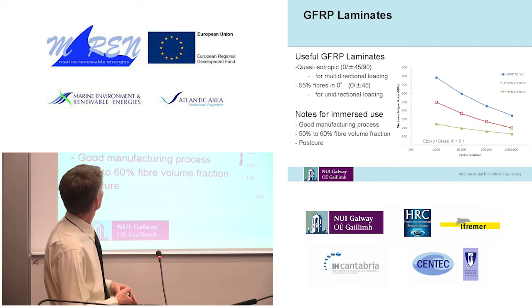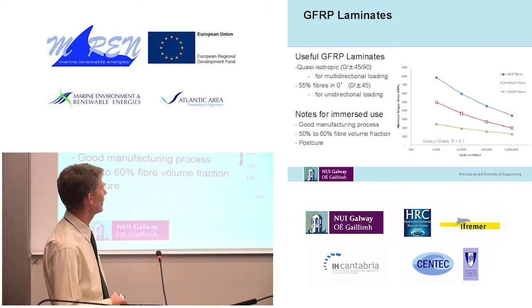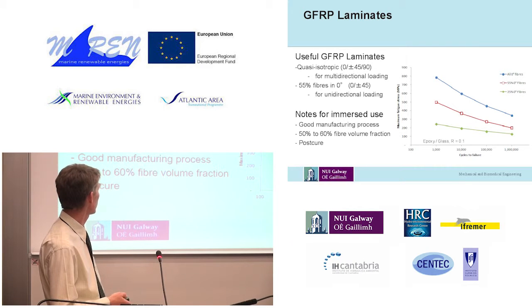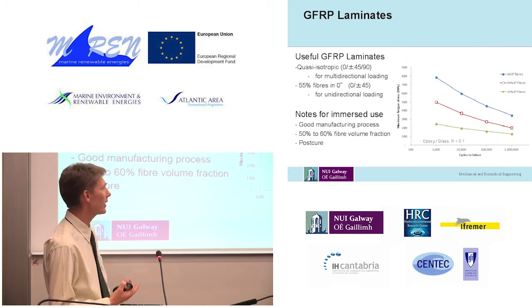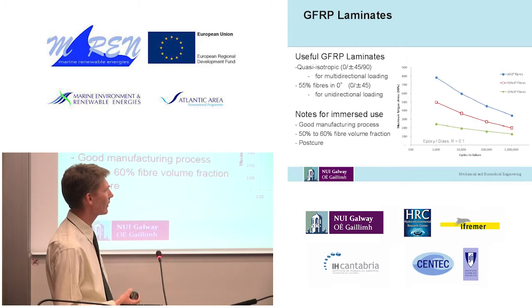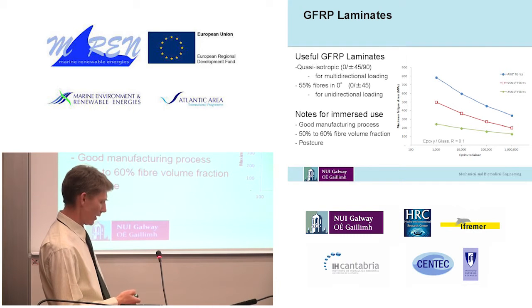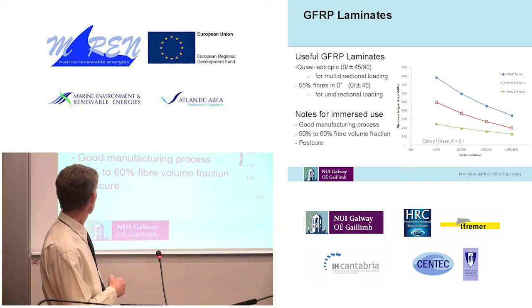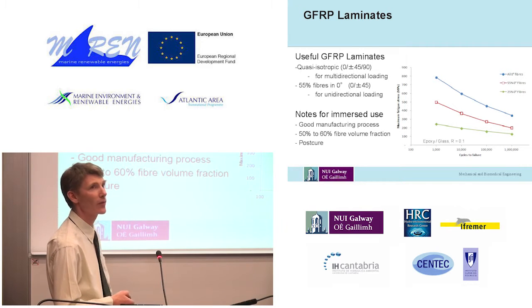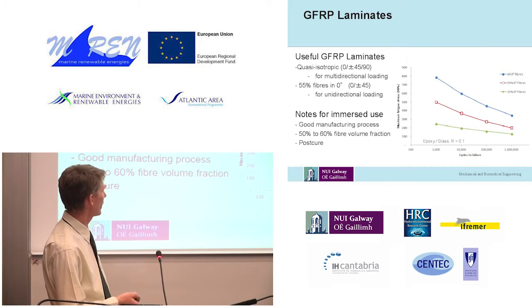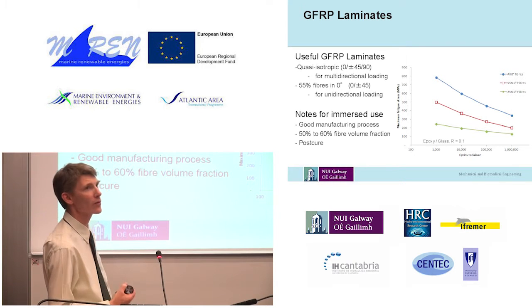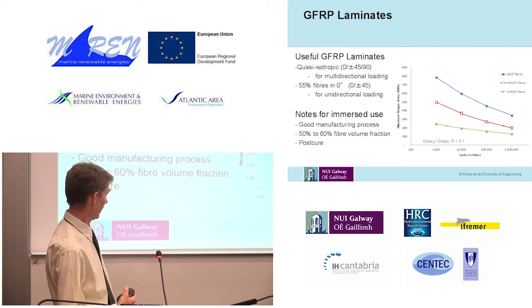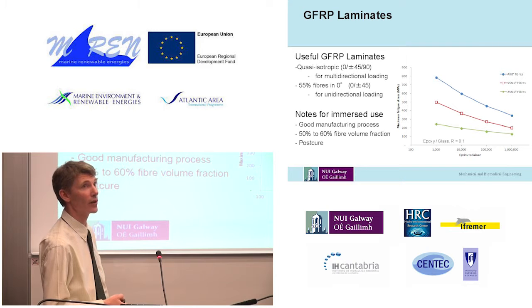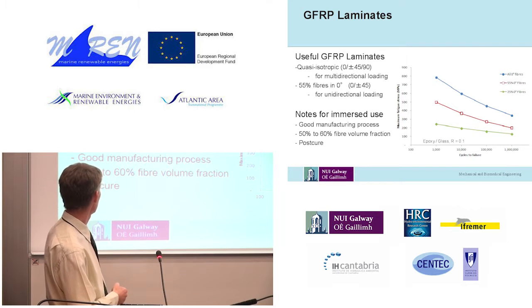The other thing is just a couple of notes about immersed use itself. It is important when you're making GFRP for use in immersed applications that you use a good manufacturing process, because voids and flaws are certainly magnified by the effects of water. The other thing I would say is it's a good thing to target somewhere between 50 and 60% fibre volume fraction in the materials, and on one hand that gets you a good strong material. On the other hand, if you start to go much above 60%, you start to have problems with the fatigue strength of the material, even though the static tensile strength would look good on the data sheet. I would tend to stay below 60%.